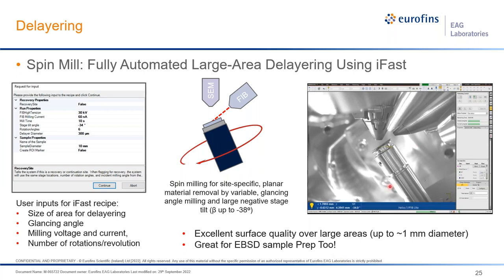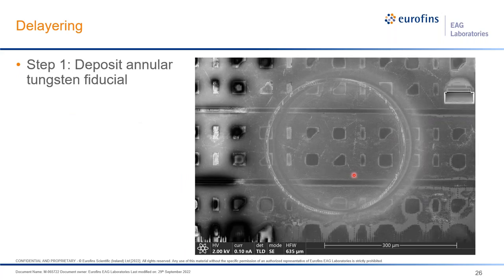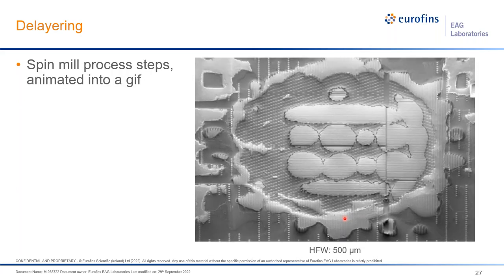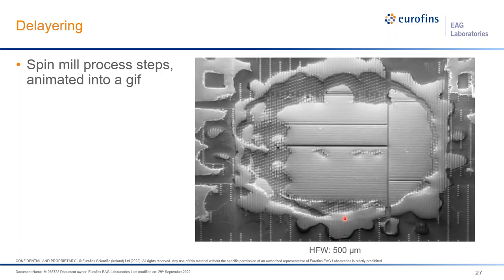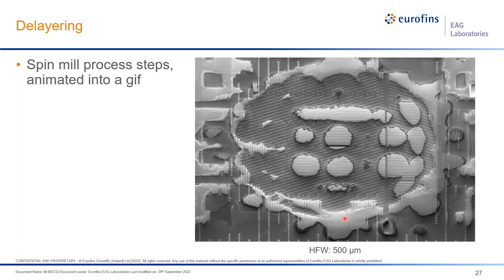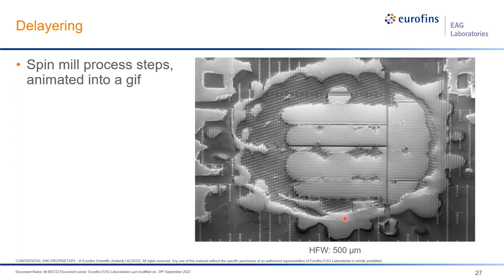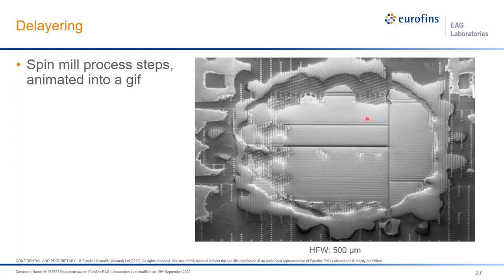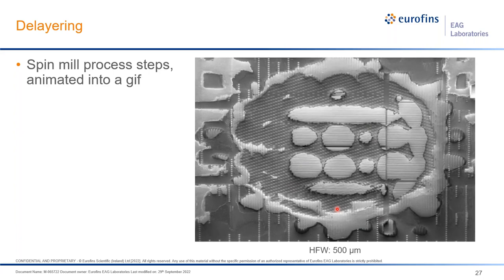And so this little video on the right was showing essentially the process of how we can spin the sample at a glancing angle using the P-FIB to clean that area up. And so I can show you just a little example of how this works. So initially, step one, we're going to deposit a fiducial reference for the area we want to do the spin mill on. And then this is just the process itself showing the delayering and how it covers a very large area, keeping a very large area planar.